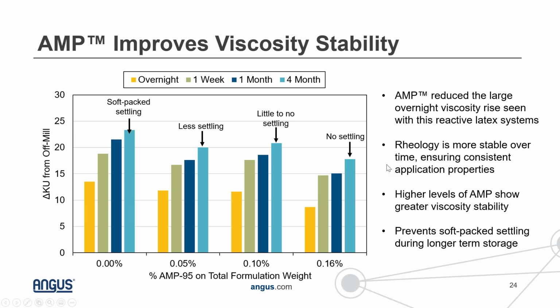stability testing, we tended to get a little bit of soft packing of the pigment particles and settling found in our control formulation. But that wasn't the case when we were using AMP. So AMP really prevented not just the viscosity rise seen in this formulation, but also some of the settling and soft packing of the pigment over time.